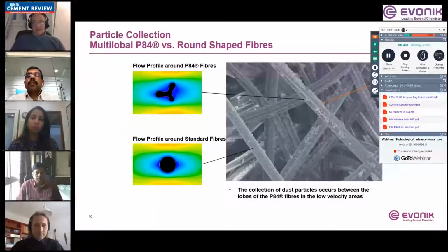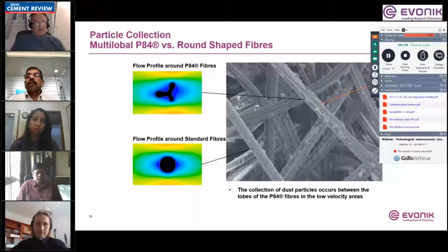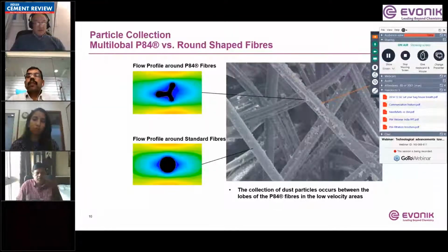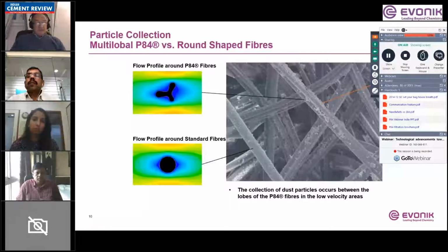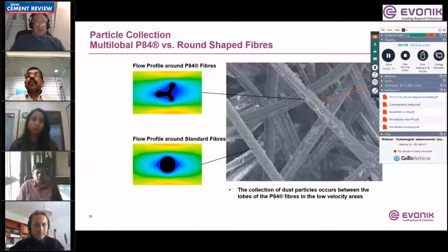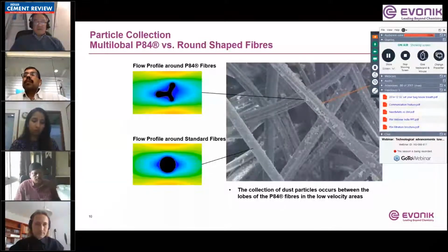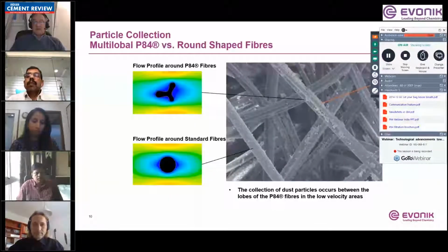But how to explain this particular high performance of P84 compared to any other fiber in the market? To do that, we have to go back to the structure of this fiber to understand its behavior. In fact, back in the 80s, we observed low gas velocity areas in between the lobes of P84 fibers. You can see on the top left image, the cross-section of a P84 fiber presents blue areas. These are the areas in between the lobes where the gas velocity is almost zero.